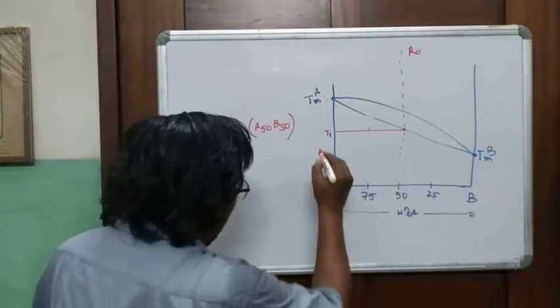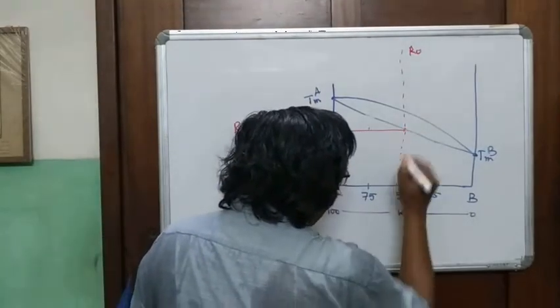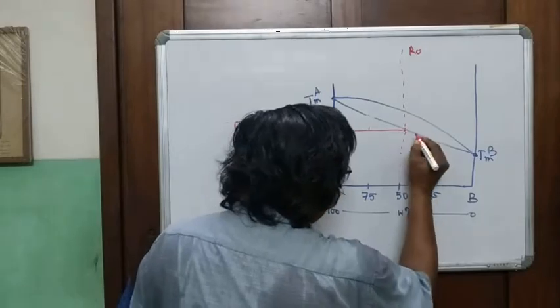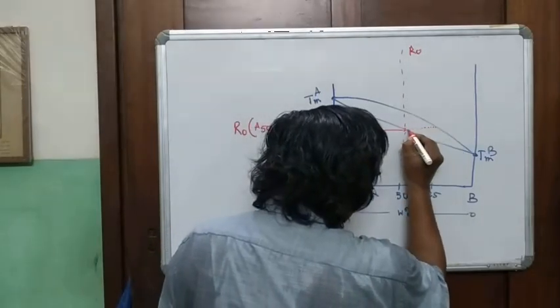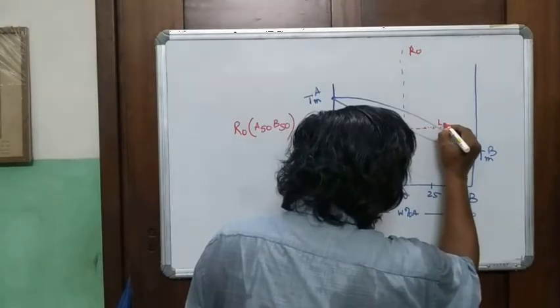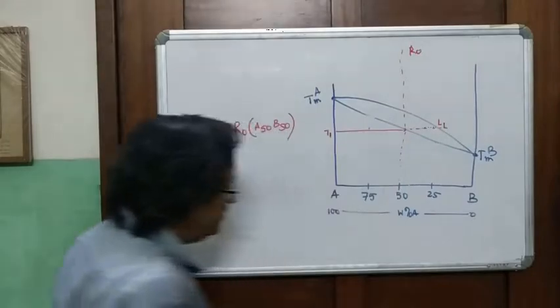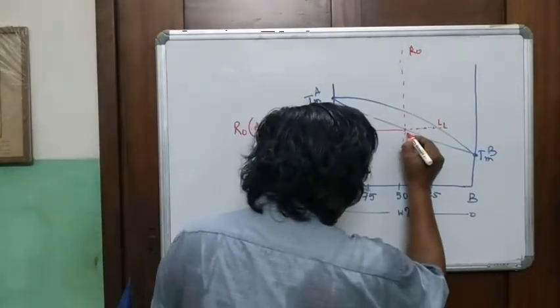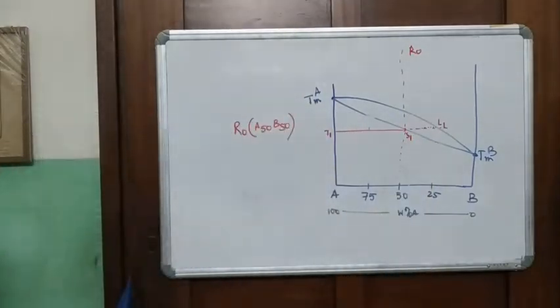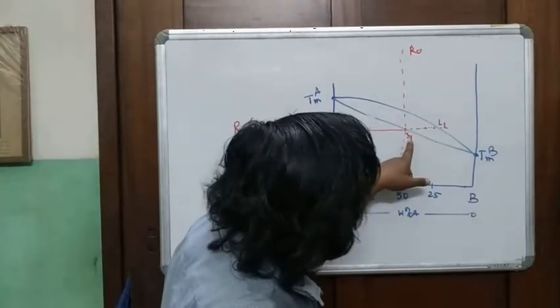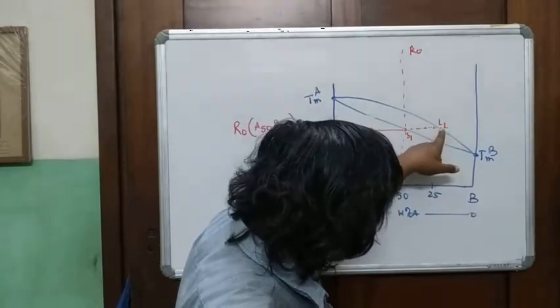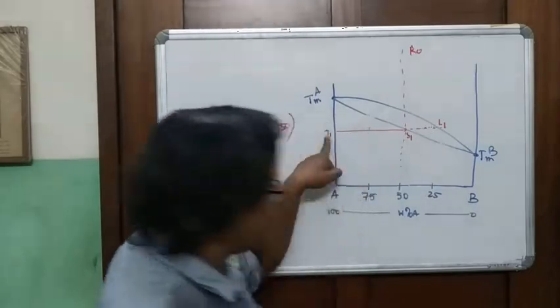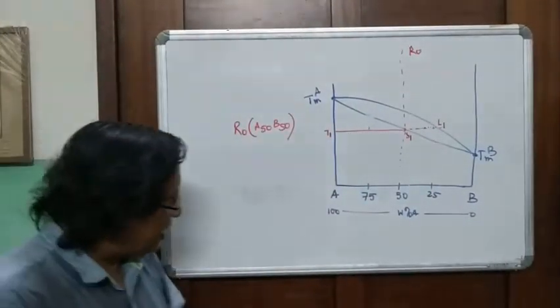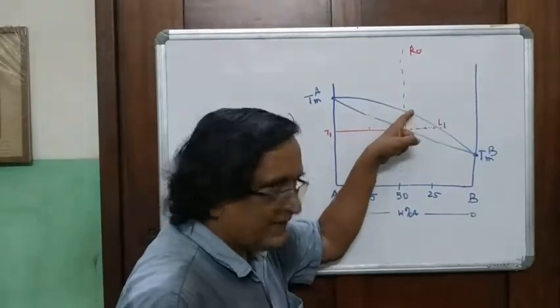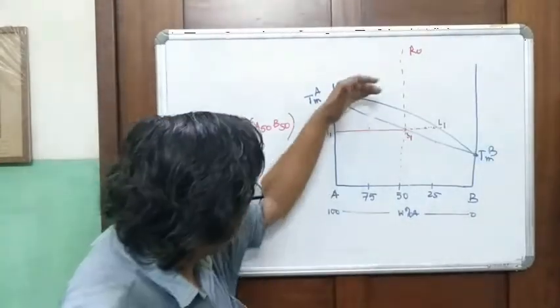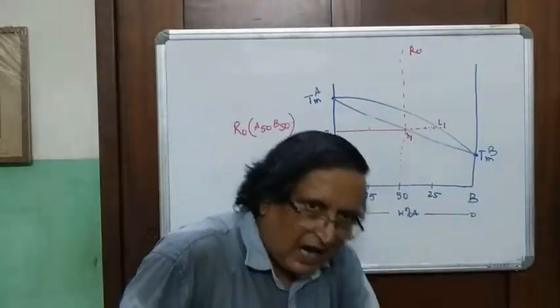So, for example, at temperature T1, this will be the composition of the solid. What would be the composition of the liquid? Very clear. You just join it. So this will be the composition of the first liquid that forms, and this will be the composition of the first solid that is in equilibrium with the liquid L1 at the temperature T1. What I tried to say before is, if you chose another composition, you would still form S1 and L1, but they would be at a different isothermal condition, at a higher temperature, if the phase had higher amounts of A.